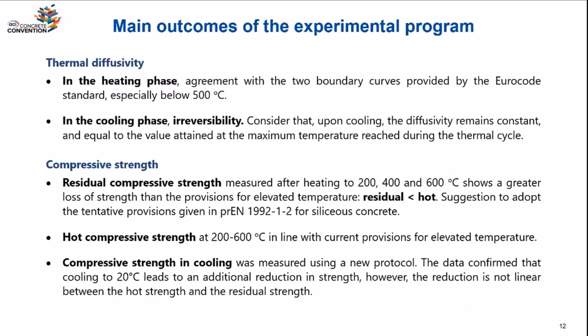So on the experimental program, really the main takeaway is that the thermal properties in the heating phase, we are fine with code provisions, but in the cooling phase, we should consider they are irreversible. So if you do a numerical simulation, you should keep the value at the maximum reached temperature, not at the current temperature while cooling. And for compressive strength, the residual value is lower than the elevated temperature value. We have additional strength degradation during cooling.